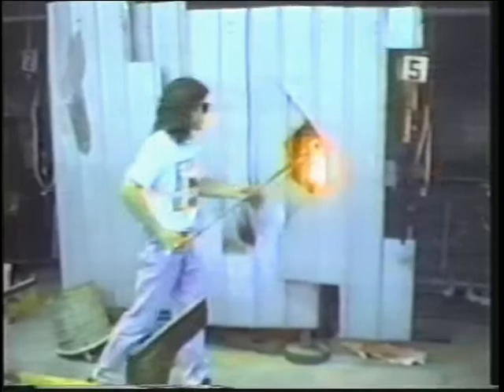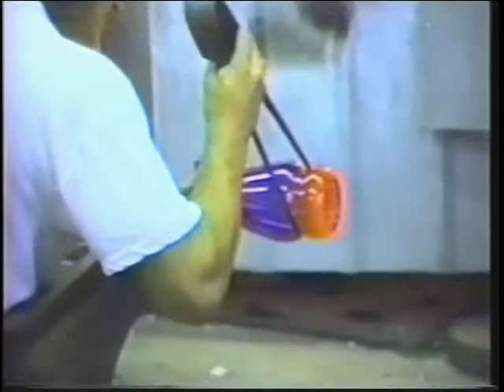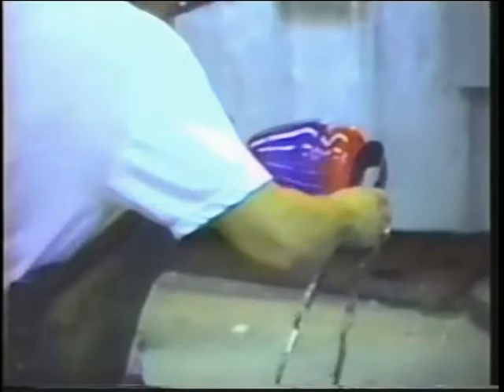What temperature are you working at, though? I mean, it's very hot in here. I can't get any closer to these furnaces. Well, the glass, when it's at a molten state, it's about anywhere between 2500 and 2800 degrees Fahrenheit. And we work the glass when we reheat it and work it and reheat it. We're working between the temperatures of about 1200 to 1800. Not as hot as when it first initially comes out of the furnace, but pretty hot where it's pliable and flexible and gravity is pulling it and we're allowed to blow it and maneuver it into a form that we want to go for.